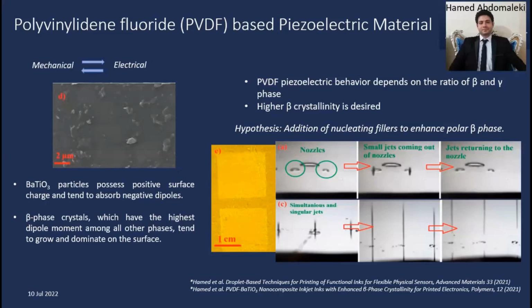So we started with PVDF, which is a polymer. PVDF is already known for its piezoelectric properties, so nothing new here. But the problem is that PVDF's piezoelectric properties are very inferior to, for example, PZT, which is the inorganic counterpart. And the idea here was to increase its piezoelectric properties, and not just increase them, but make it a printable dispersion. So we wanted to print this material. There's no commercially available piezoelectric material that can be printed right now.